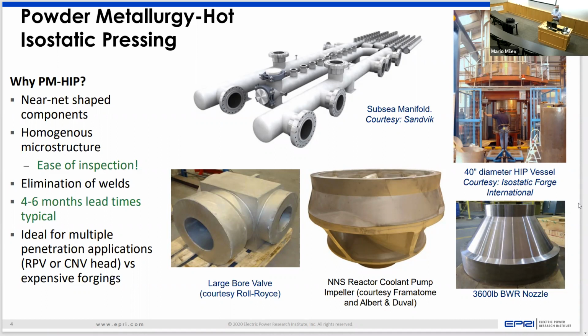What I'm showing here are some of the large structures that have actually been produced. There's a large valve body that's been produced by Rolls-Royce. You see a reactor coolant pump that's made by Framatome and Aubert & Duval. We've done a good bit of work on some fairly simple geometries initially, and you'll see some pretty complex geometries in a moment. And this manifold up in the top has actually been made in a few different sections and welded together. But again, what it does is it allows you to eliminate a lot of the interconnections within some of these and the welds that have to be made. It makes them as a single monolithic structure.